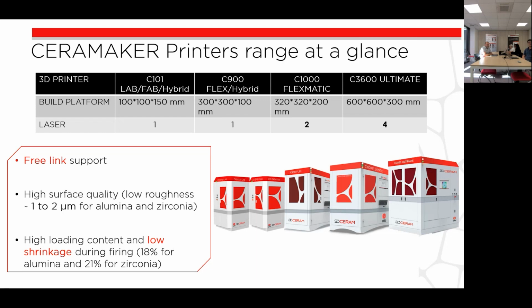The advantage of SLA technology is that you can use link-free supports because of the way that we build parts. We go bottom to top, so we don't need links between the support and the part, because the parts sit directly on their support through fabrication and then through debinding and sintering, if they were supports for sintering. With SLA, you end up with a high quality surface, with roughness of around 1 to 2 microns for alumina and zirconia. We have slurries with a high loading content, around 50 to 60%, and so low shrinkage during firing. Just as an example, you get 18% for alumina and 21% for zirconia.